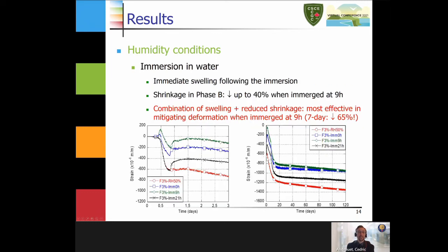But even more interesting is what happens when we immerse the specimen in water. First, we see that we have an immediate swelling following the immersion. For example, we can see here, if we immerse the specimen at 9 hours or at 21 hours, we have an immediate swelling following the immersion. And even more interesting is that the shrinkage in phase B when the specimen is immersed in water is reduced by up to 40%. So when we combine the effect of the swelling and the reduced shrinkage, we have a very effective way of mitigating the deformation when the specimen is immersed at 9 hours. And we see at 7 days a reduction of shrinkage up to 65%, which is really significant.